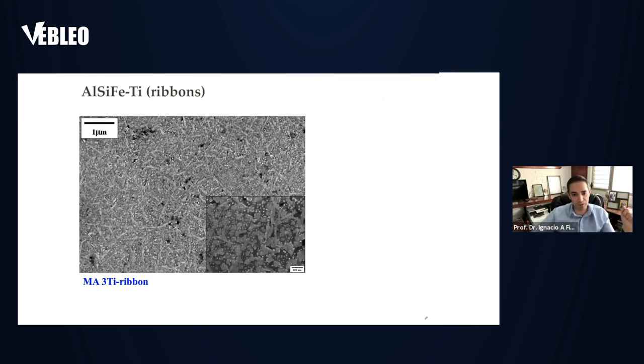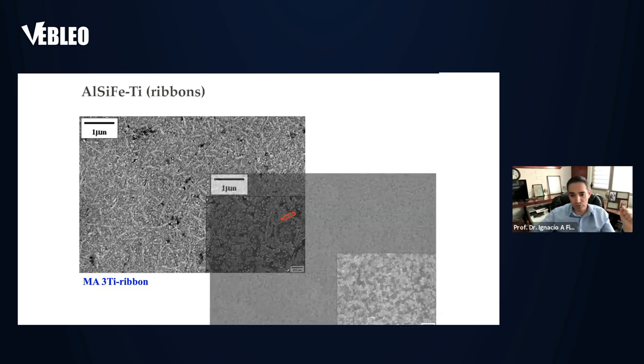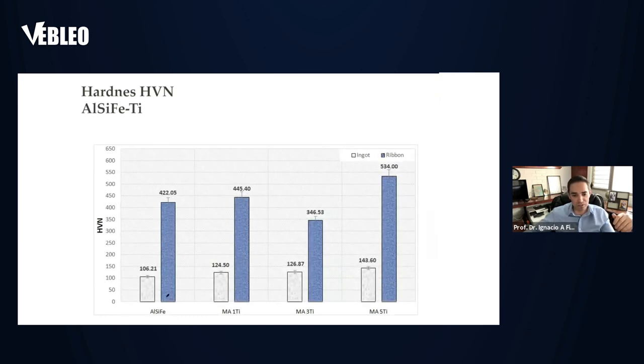With 3% titanium in ribbons, I can hardly see any acicular structure — intermetallics are around 100 nanometers. Moving to 5% titanium, the acicular structure completely disappears — everything is spherical. That was one of the main contributions of this research, of great interest to the company. Checking the micro hardness: at 3% titanium it drops — because the microstructure was still quite acicular with many needle-shaped stress concentrations. However, at 5% titanium with the same melt spinning process, the stress concentrations disappear completely, giving a more homogeneous structure, and the micro hardness was the highest of all.